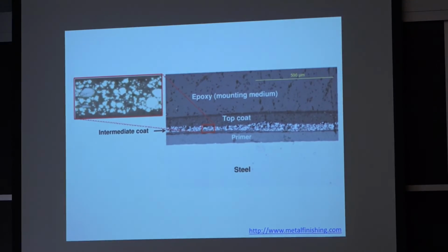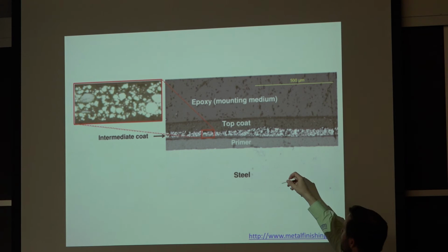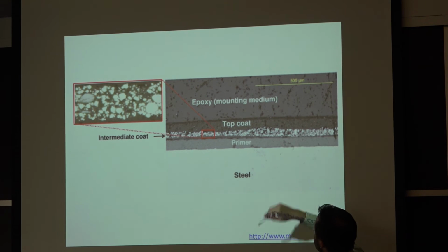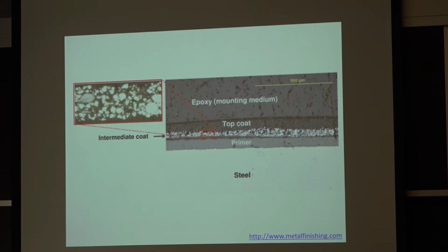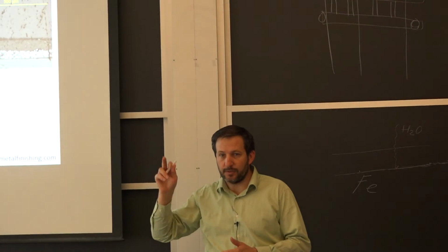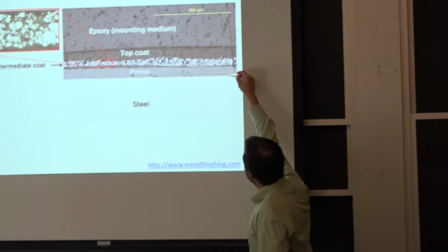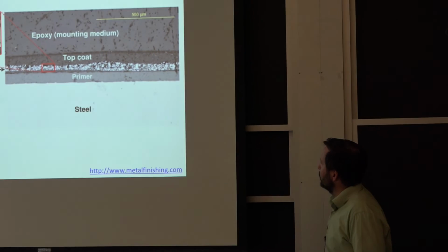That's just an example of, I guess, a more complex coating where they have the steel, they have the primer, and then they put this zinc coating. So zinc paint. We couldn't verify for sure that the primer was going to be effective here. I think that was a mistake, because if you have your sacrificial element so far from the steel surface, you need the primer to be conductive, and you need the ions to be circulating all the way from the primer to the other interface. So this was probably a mistake where they should have put the zinc-rich layer straight on the steel, and in this case, let go of the primer.